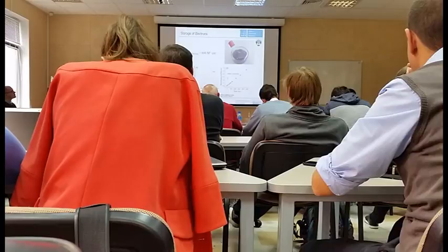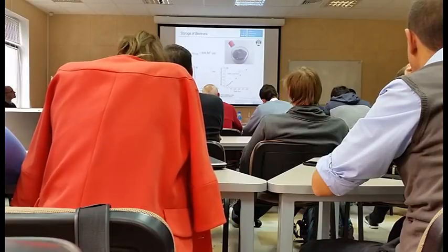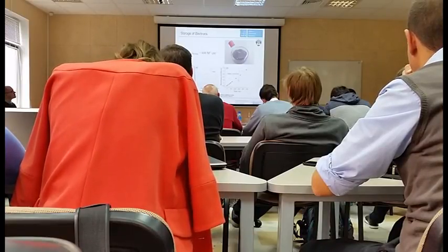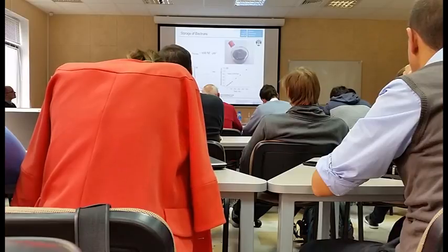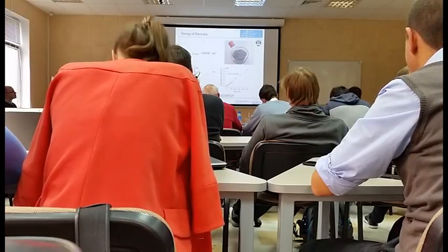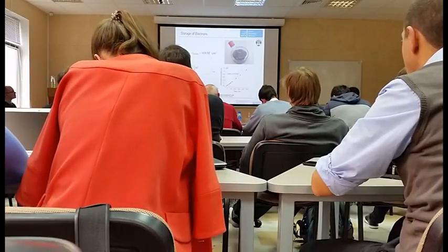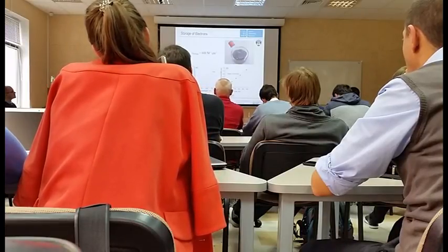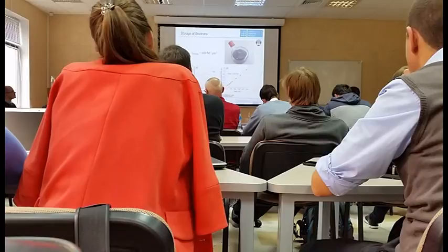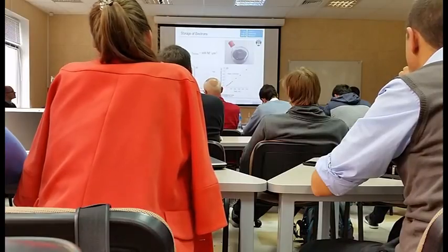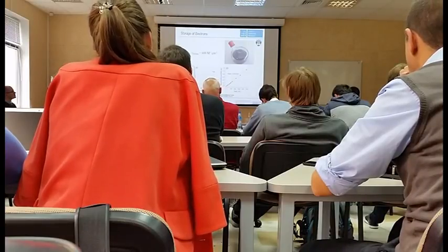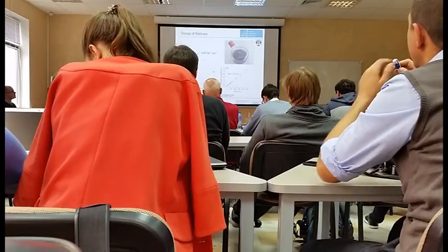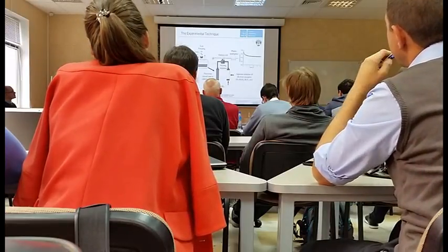You can determine the rate, and you can determine the extinction coefficient, so you know exactly how many electrons you have per particle. And per nanoparticle you can have 20, 30, 40 electrons easily on a single particle, and then you have this three-dimensional network. So multi-electron transfer processes should be easy to follow.